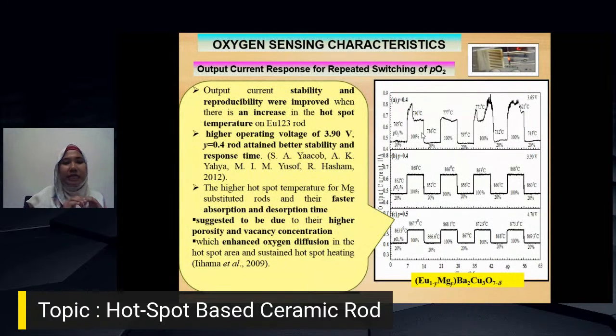So you can see the stability of the current when the substitution of the magnesium in the compound increases. So the stability will improve, the reproducibility will improve when you have a higher substitution of the magnesium. And also it's very important to focus on the operating voltage; the higher operating voltage is also important.